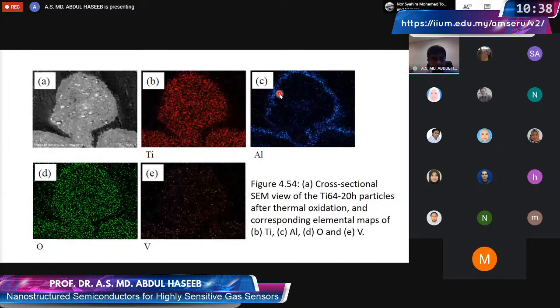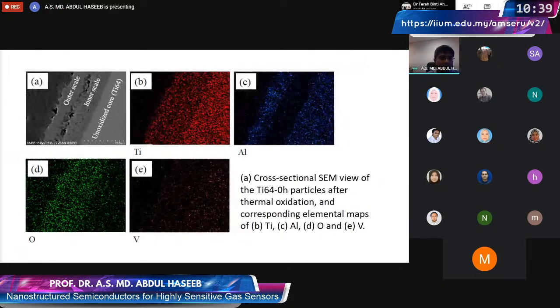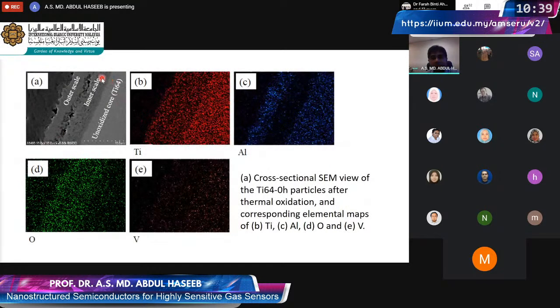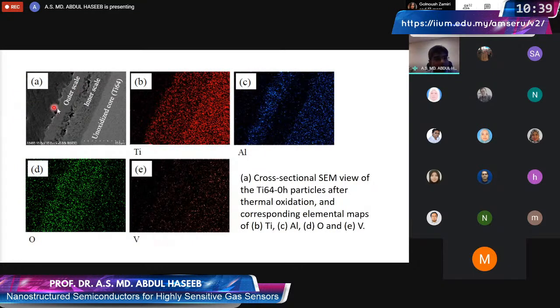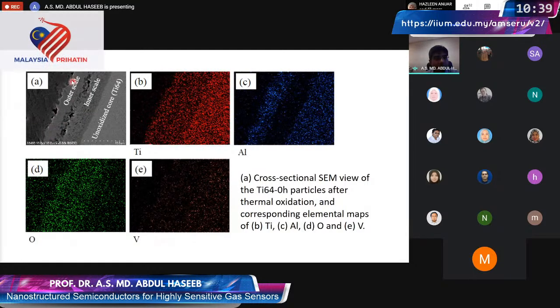And I may not be able to explain all this, but let me just tell you what happens. So everything happens at the surface. And the process of this nanowire formation is a little bit complex. So when you do the oxidation, segregation of things happens at the surface. And we see that aluminum, the blue one, tends to segregate at the surface, and it creates complex layers, in fact. So an inner scale that contains titanium and the outer scale that contains an aluminum and titanium mixture. And on that surface, the nanowires grow. So nanowires grow on this particular surface. And before the nanowires grow, a lot of other things also happen.